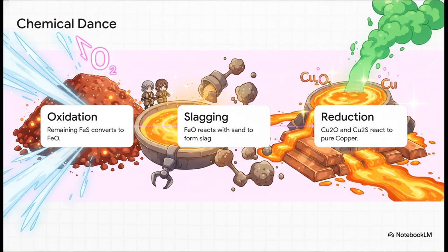First, that intense blast of oxygen converts any lingering traces of iron sulfide right into iron oxide. Second, just like in the smelting furnace, that iron oxide reacts with the sand we added to form more of that liquid iron silicate slag, which is safely skimmed off. Finally, step 3 is the grand finale. The remaining copper oxide and copper sulfide compounds are forced into close contact, and they violently react with each other. It's an incredible self-reaction, where the ore essentially tears its own bonds apart. This auto-reduction breaks the final chemical chains, yielding isolated, pure elemental copper, while blowing off the very last of the sulfur as sulfur dioxide gas.